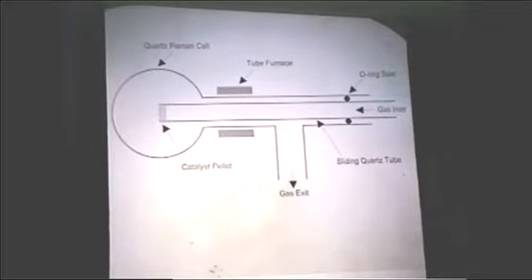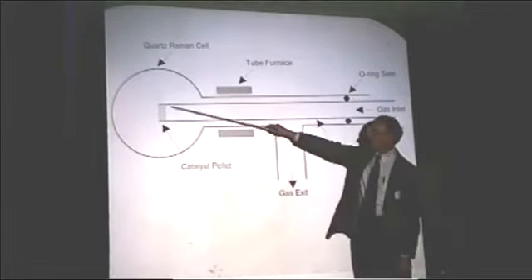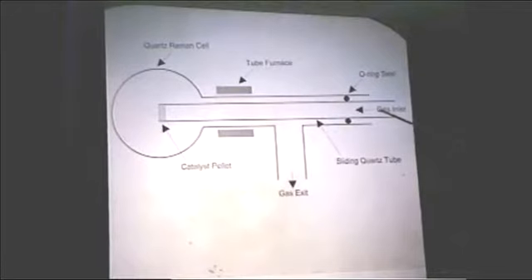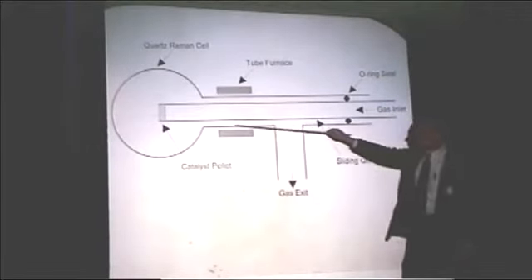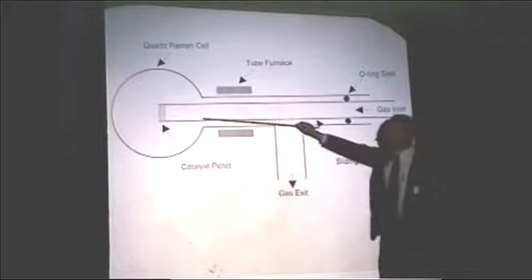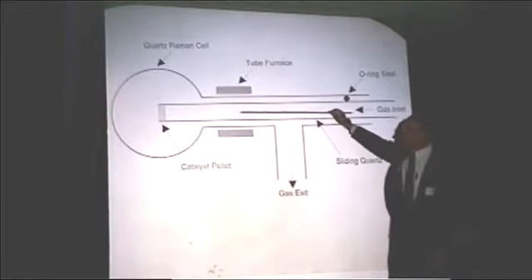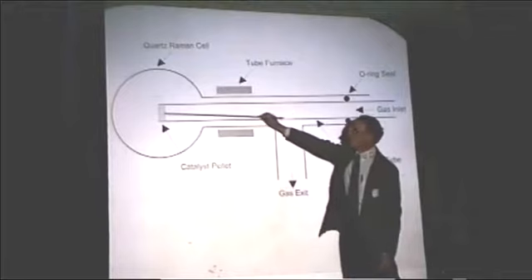So in order to do this, you need some way of coking your catalyst in a controlled way. So Lee built a little simple Raman reaction cell here. This is just a quartz cell. We have a little quartz tube, which is about 1/4 of an inch in diameter, and we just mount a catalyst pellet across the end of the tube. We have a gas flow that goes through the pellet and back out through an exit, and then we can simply move this back and forth between a heated region where we can coke and a measurement region where we can make a measurement. So it's a controlled atmosphere cell.